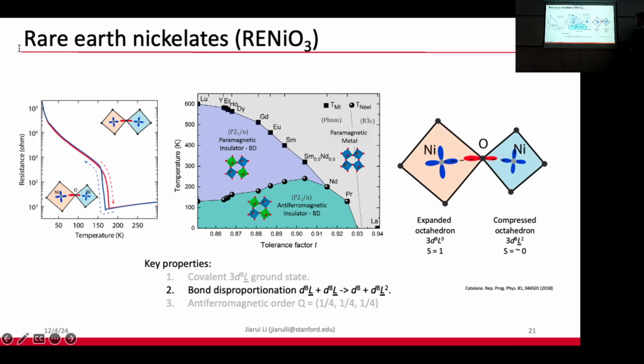And the mechanism for it to go through this metal to insulator phase transition is that at high temperature, these 2 nickel sites are equivalent, but in the low temperature phase, the oxygen will break this symmetry between these two nickels, and move towards one nickel more than the other, forming an expanded nickel oxygen octahedra and a compressed nickel oxygen octahedra. And you will also grab one electron from this nickel and put it on the other nickel, forming 3d8, L0, and L2. So this is called bond disproportionation. And this is equivalent to forming a three-dimensional checkerboard lattice of, say, a charge density wave that opens up an energy gap at the Fermi energy that makes it an insulator.